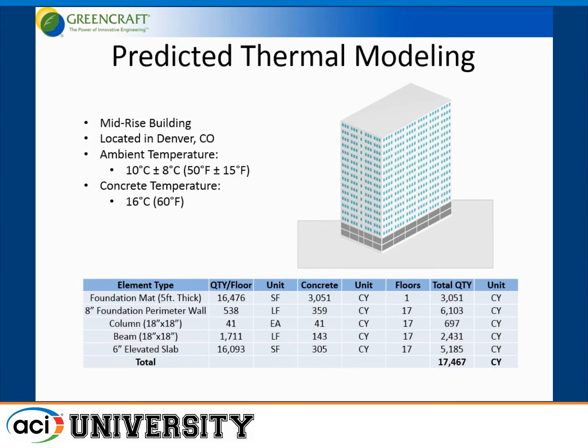So what we did is we said, hey, we're gonna go to Denver. We wanted to do a thermal modeling of a structure that could be right here downtown Denver. So this is a 15-story building that could be an office building, a hotel, condominiums. We modeled this for a spring construction schedule where the ambient temperature was 50 degrees Fahrenheit plus or minus 15, you know, daily temperature fluctuations. The placement of concrete temperature was 60. We broke it down between all these elements. We have a 5-foot thick mat foundation and about 17,000 cubic yards of concrete.